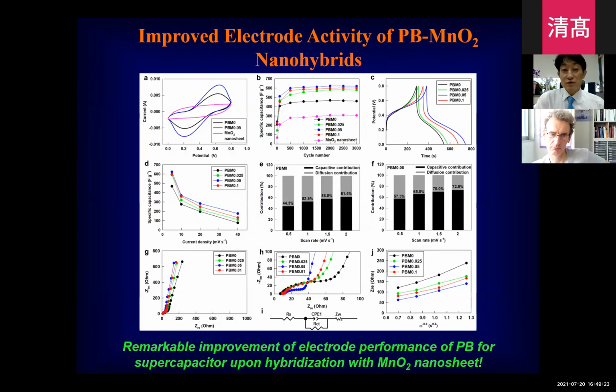Also, we apply those materials as a supercapacitor electrode. As you can see here, we can confirm the significant enhancement of electrode performance upon the hybridization with the manganese oxide nanosheet. I want to emphasize the amount of manganese oxide nanosheet is not that big, but the effect is very significant. As you can see here, such a hybridization is quite good to enhance the charge transfer kinetics of Prussian blue.